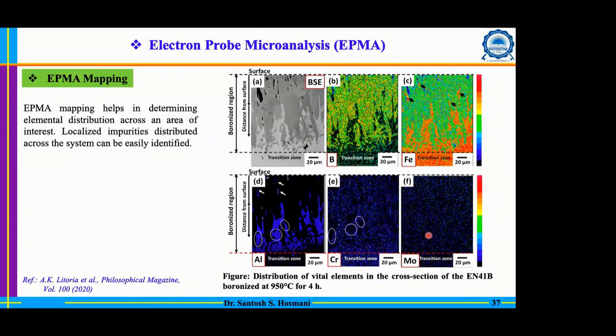Now, this rejection kinetics, or the rate at which these elements are rejected, will be different for different elements. And that's why, near the boride column, you can see the elemental mapping here. If you look at figure B, it clearly shows that we have a high boron region, that is, the boride column is there. And you compare with figure D, where this boride region is appearing dark. That means there is no presence of aluminum there.